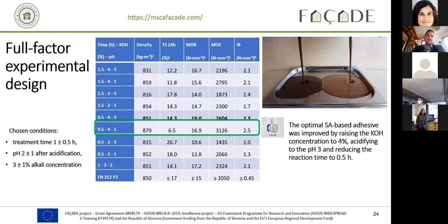When the preliminary parameters were set, we created a full factorial experimental design using treatment time, pH, acidification, emulsification and alkali concentration as variables, while density, thickness swelling, modulus of rupture, modulus of elasticity, and internal bonding were used as response functions. The result showed that the optimal suberinic acid-based adhesive was obtained by raising the potassium hydroxide concentration to 4%, acidifying to pH 3 and reducing the reaction time to half an hour.